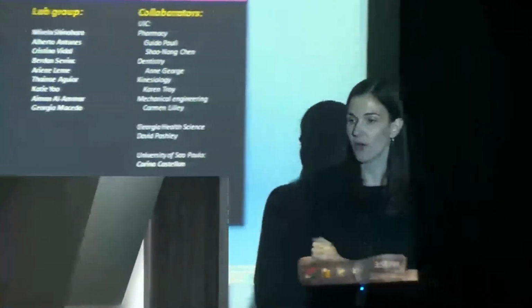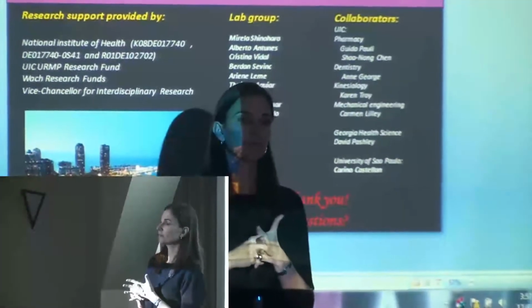Basically, we saw two aspects. In the first study, we created a lesion and we tried to remineralize it. And in the other one, we used it to prevent the lesion from developing. So you kept treating the surface of the tooth and inducing this acidic environment. And for both, we saw a positive effect of the grapeseed.